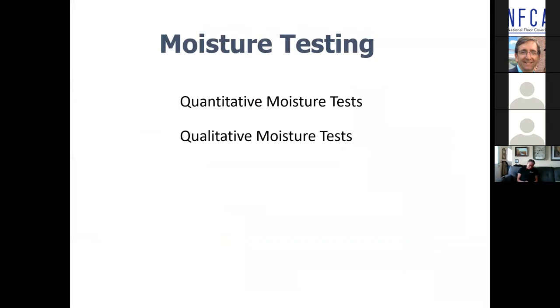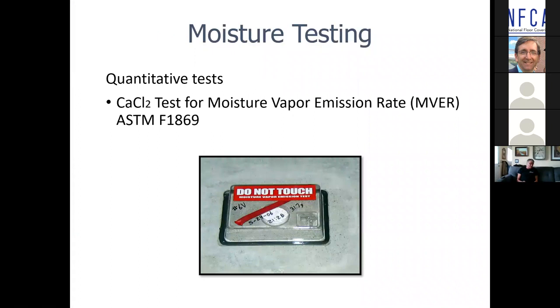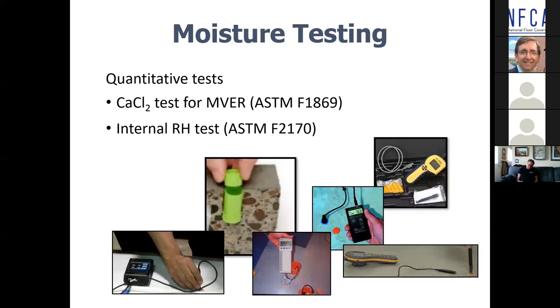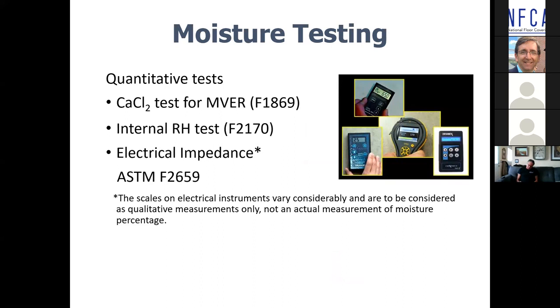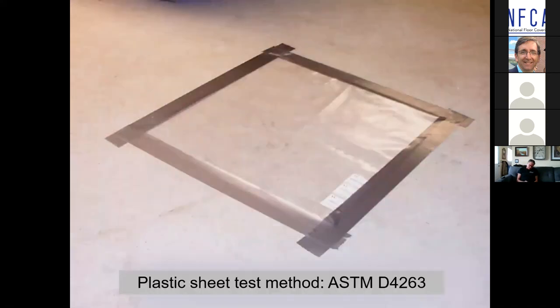The tests that we perform for moisture fall into two categories: those that actually give us a number and those that basically just tell us whether it's wet or dry. On the quantitative side, historically used for decades and decades, going back into the 30s and 40s in its crudest form, was the measurement of the moisture vapor emission rate by what's referred to as the calcium chloride method. In 2002, in the United States, we adopted the European method of measuring moisture in concrete floor slabs, F2170. And we also introduced the relative measurement of moisture by electrical impedance, ASTM F2659.